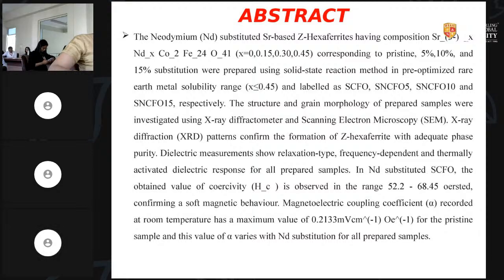using solid state reaction method in the pre-optimized rare earth metal solubility range where x is less than or equal to 0.45, and labeled as SCFO, SNCFO5, SNCFO10 and SNCFO15 respectively. The structure and the grain morphology of prepared samples were investigated using X-ray diffractometer and scanning electron microscopy. X-ray diffraction pattern confirms the formation of Z hexaferrite with adequate phase purity. Dielectric measurements show relaxation type, frequency dependent and thermally activated dielectric response for all prepared samples. Then the introduction.